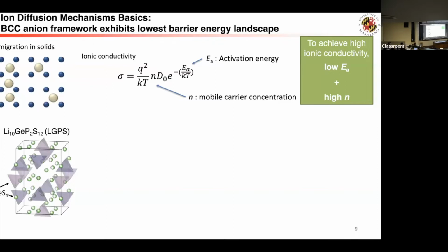So certainly the lower is better, especially since this has the exponential factor. And the other one is the carrier concentration, essentially how many lithium ions can move at the same time. So the higher number is the better. In a typical solid, this barrier is high and this number is low. And this LGPS material is a compound that will be shown as our best performing.